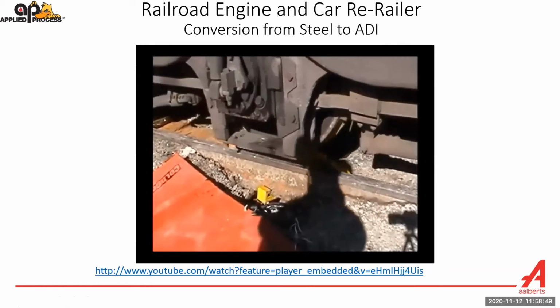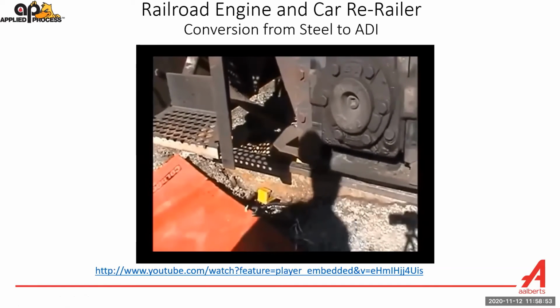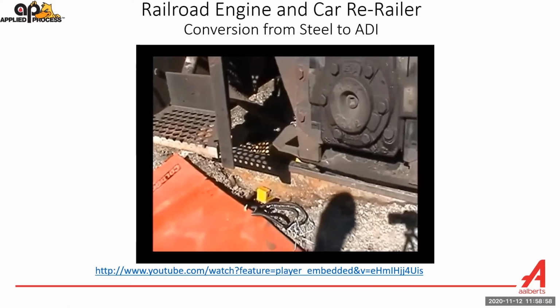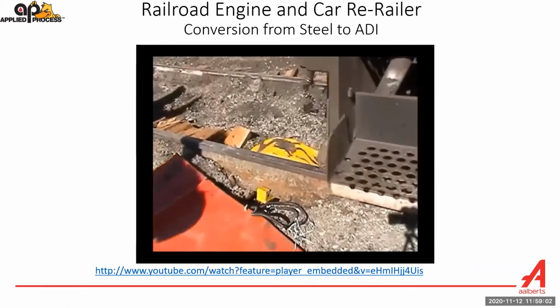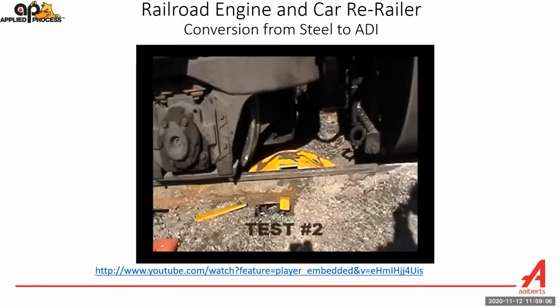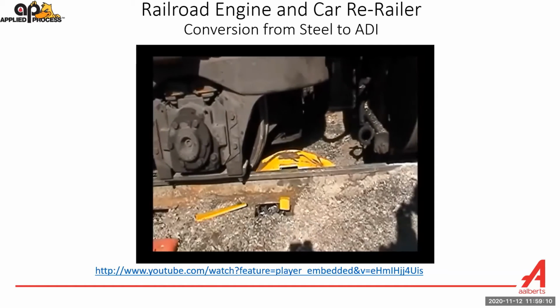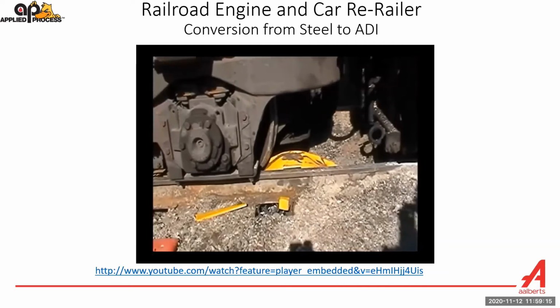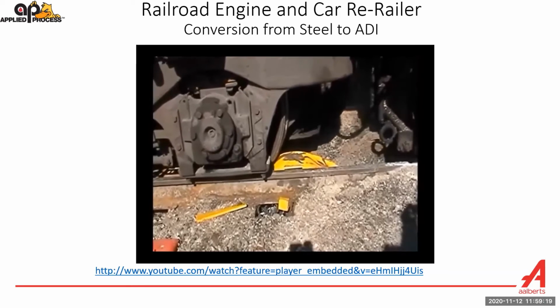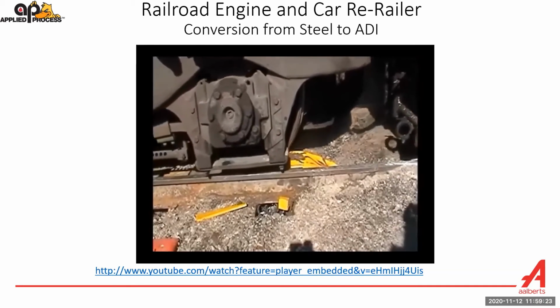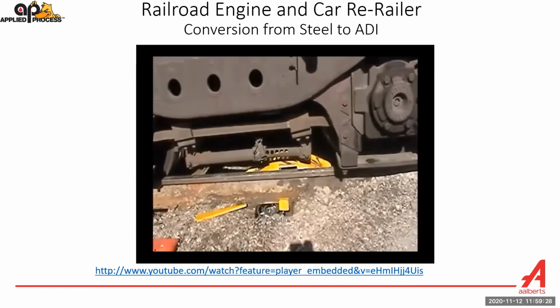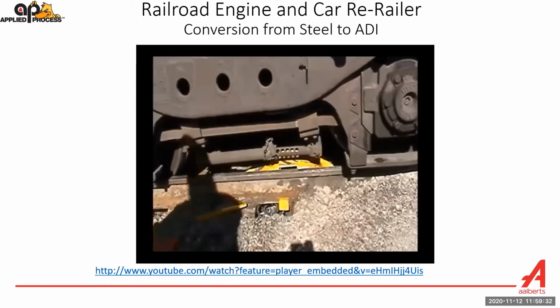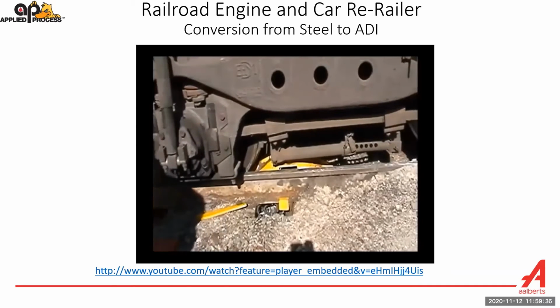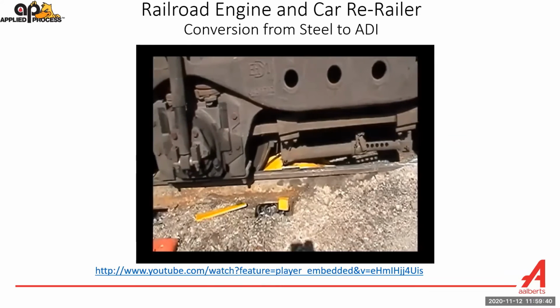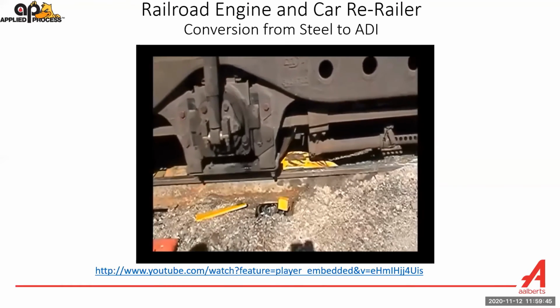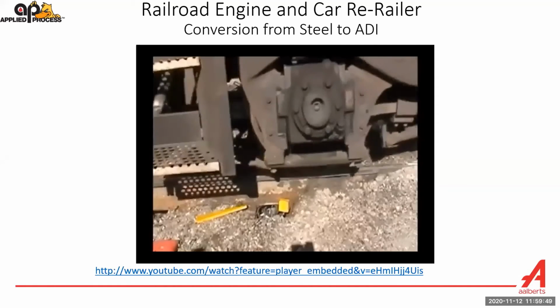The wall thickness on these castings is about 5/8 of an inch thick, and on the inside there's a series of gussets to improve the load carrying capacity. So they use finite element stress analysis to understand how to optimize the design of the component. And the key on this portion of the video is watch the last wheel hit. It takes a significant blow right at the end there.